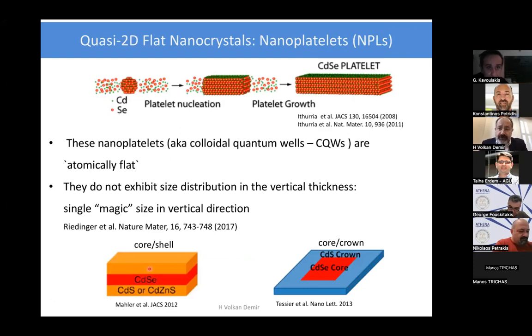So with all this happening, we were very excited and inspired by this work from CNRS, France. Our friends and colleagues there found ways to reproducibly produce these atomically flat structures. And they demonstrated that one can actually have magic size vertically in a single batch. And this is, of course, important because the tight confinement is in the vertical direction. And we use significantly this quantum confinement while we can grow the structure laterally. So geometrically, we can make them large.